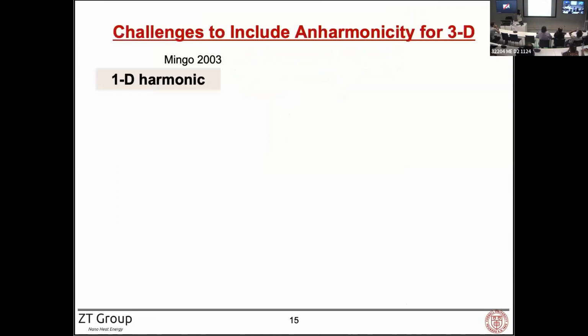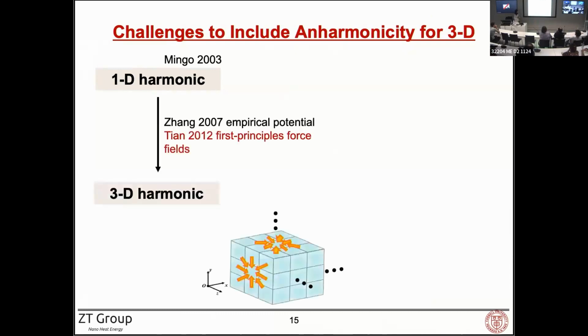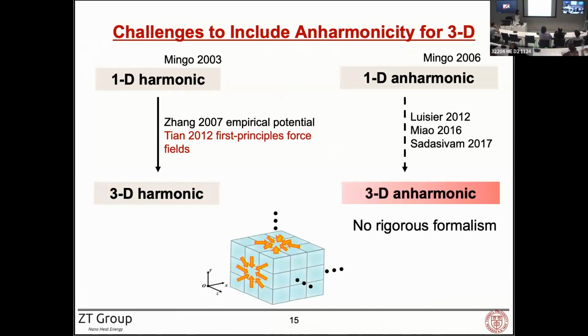When Mingo first introduced the atomistic Green's function in the harmonic framework, it was for a 1D structure. It wasn't that challenging to extend it to the 3D structure. Mingo also introduced a framework for the 1D atomic chain including anharmonicity. But to go from 1D anharmonic to 3D anharmonic is significantly more challenging. There were different efforts to extend it to 3D, but different levels of assumption were made. So we wanted to look at this problem by developing a rigorous formalism where we can include the first-principles force constants, for both second order and third order, into a framework to accurately describe the phonon scattering at the interface.